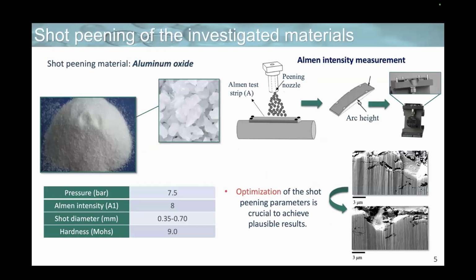The shot peening treatments were performed using an air blast type of machine with aluminum oxide as the shot peening media. Prior to the shot peening of the specimens, the Almen intensity measurement has to be conducted to enable the desired Almen intensity. And this is done simply by fixing an Almen strip on a probe holder and shot peening with the desired set of parameters, which will then induce the arching of the strip. And then by using the gauge meter, we measure the difference in the height between the flat strip and the arched strip. And this gives us our Almen intensity.